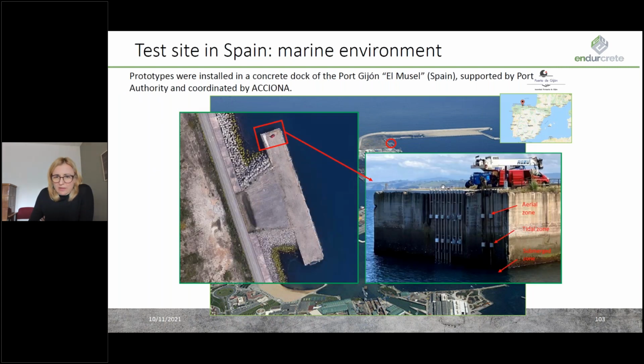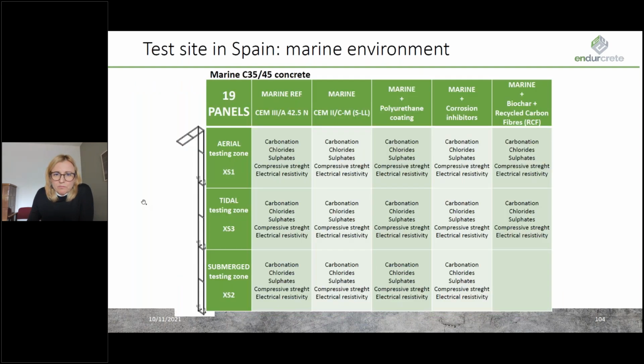We can see on this slide how the steel frame was used for holding the panels in different zones, from aerial zone, tidal zone to the submerged zone. In this site, two cement types were used. First of all, the reference cement was CEM3A 42.5N, and the EnDurCrete cement CEM2CMSLL. Additionally, the technologies developed in EnDurCrete were used: polyurethane coating, corrosion inhibitors, and biochar with recycled carbon fibers.